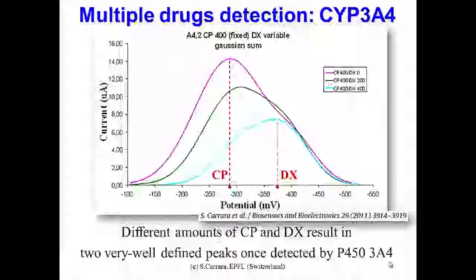You can see that we can clearly distinguish two different peaks in the sample. However, if we fix the concentration of cyclophosphamide at 400 micromolar, and vary only the dextromethorphan in our sample, we get variation in the peak related to the dextromethorphan, but we also observe different current on the peak of cyclophosphamide. So in this case, the presence of the dextromethorphan has partially inhibited the detection of the cyclophosphamide.